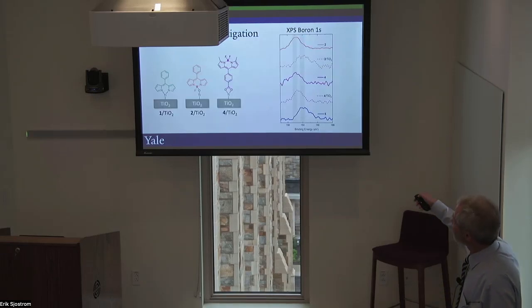How is it binding? One way to study this is by using X-ray photoelectron spectroscopy, which is a technique that looks at the ejection of electrons from an element of interest, in this case boron, and the energy tells us some information about what kind of coordinating environment it has. And so this is just showing this molecule here, the BODIPY, and by itself free in solution it has an X-ray photoelectron spectral energy of around 193 electron volts. But when we bind it on TiO2, it shifts by about 1 electron volt.